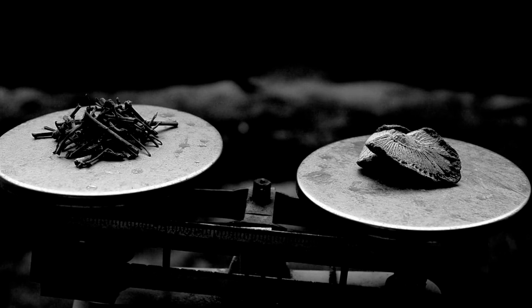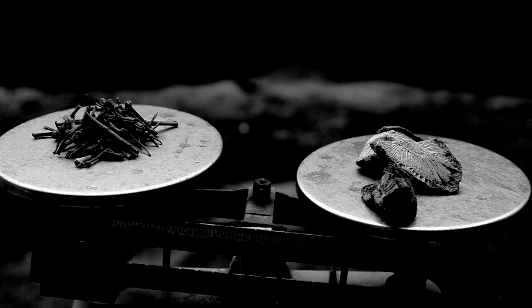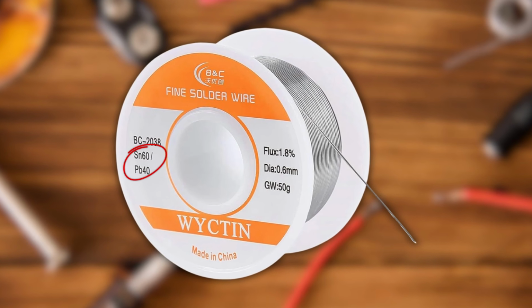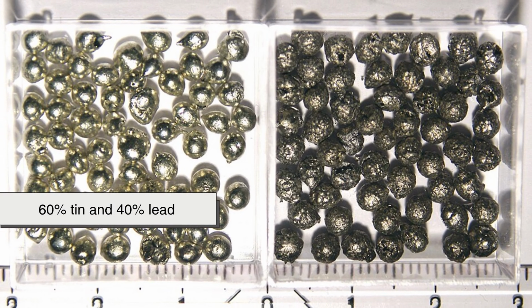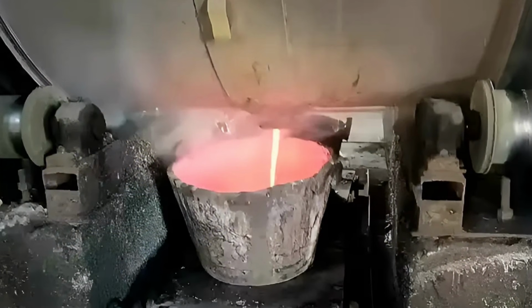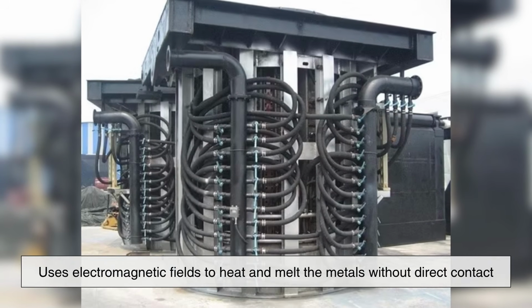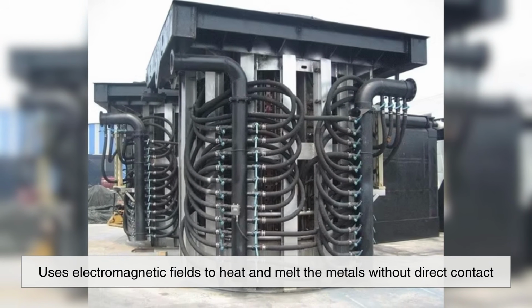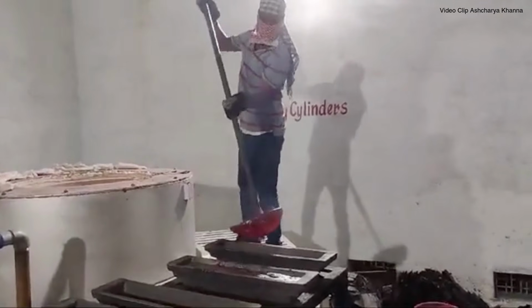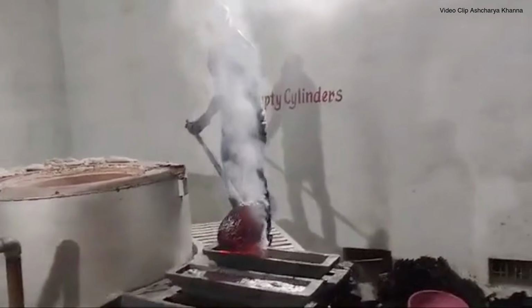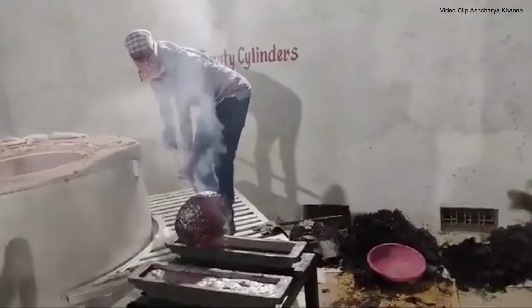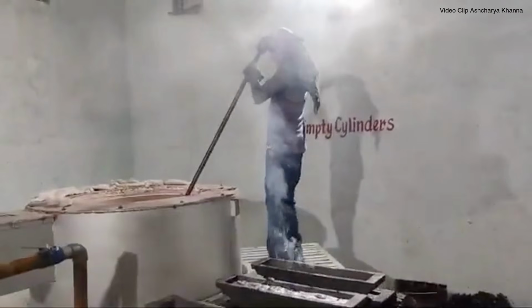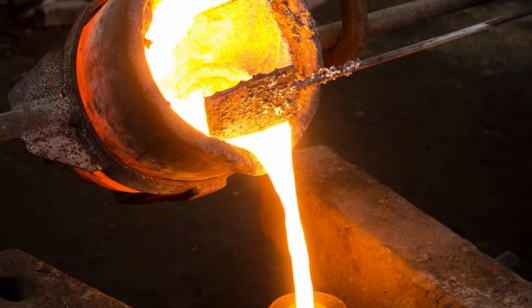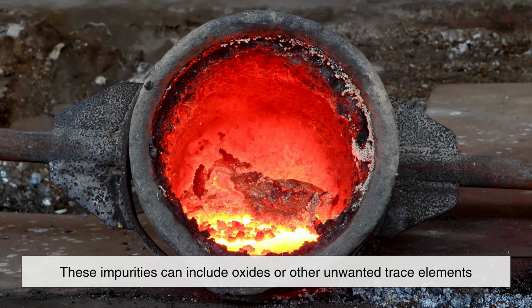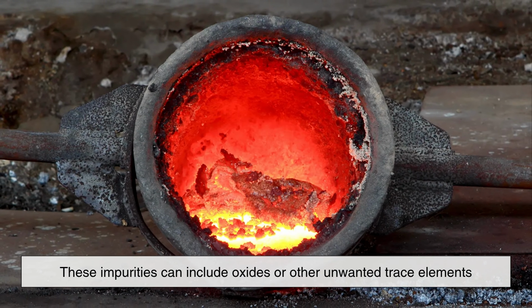At the factory, the metals are weighed in precise ratios according to the desired alloy composition. For example, the classic 60/40 solder, that's 60% tin and 40% lead, is mixed accordingly. The metals are loaded into a large induction furnace, which uses electromagnetic fields to heat and melt the metals without direct contact. As the metals melt and combine, technicians monitor temperature and composition carefully to ensure uniformity. This molten alloy is kept at a specific temperature to maintain its fluid state and to allow any impurities to rise to the surface, where they are skimmed off. These impurities can include oxides or other unwanted trace elements, which would otherwise compromise the quality and performance of the solder.